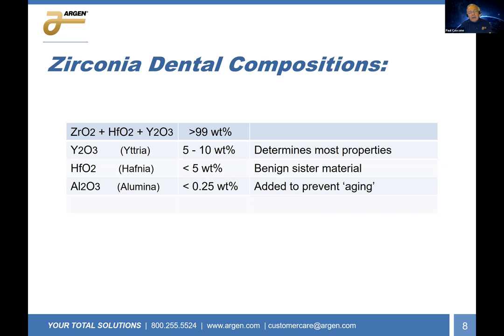So the modern zirconias have like 0.05% or even less alumina in there, and that gives us the quality we want with regard to preventing the aging reaction, yet it doesn't impact the translucency. Now, this other element that we call yttria is there in order to stabilize the zirconia, and we'll talk more about that later. And generally, in the present-day zirconias, it's in there between 5% and 10%.